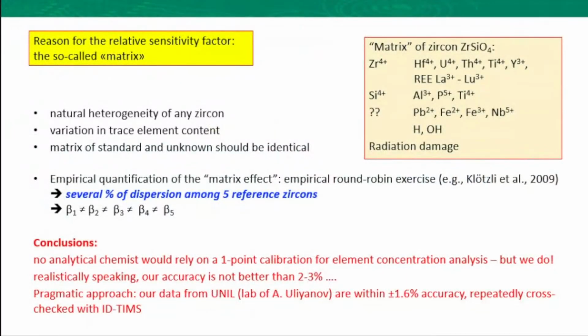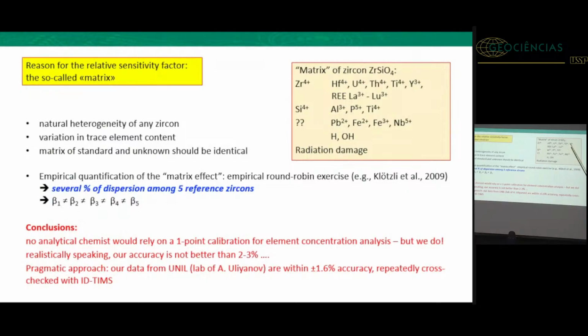The reason for the variation of this relative sensitivity factor is the so-called matrix. Everybody speaks about matrix effects, but what is this actually? Matrix is the trace element composition of zircon. So we have a series of ions which are replacing zirconium 4+. Some of them are 4+, some of them have different valence, mostly the rare earth elements. And then we also have some ions which are replacing silicon on the 4+ site. So also here we have some offsets in valence. We have to compensate. We can compensate with weird elements like 2+, 3+, but also 5+. There's quite a bit of niobium in some zircons. And it can also be compensated by H, hydrogen or OH groups. And then we have radiation damage, which is a completely different thing. We'll come back to this.